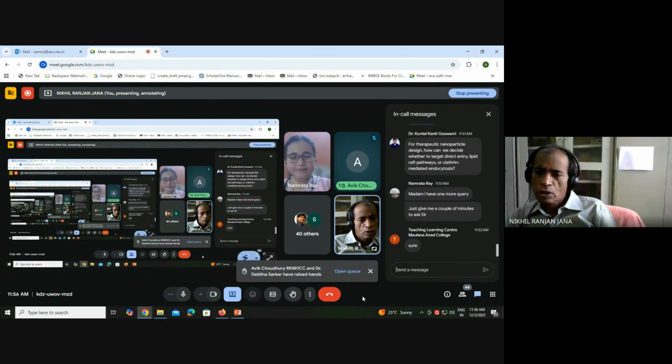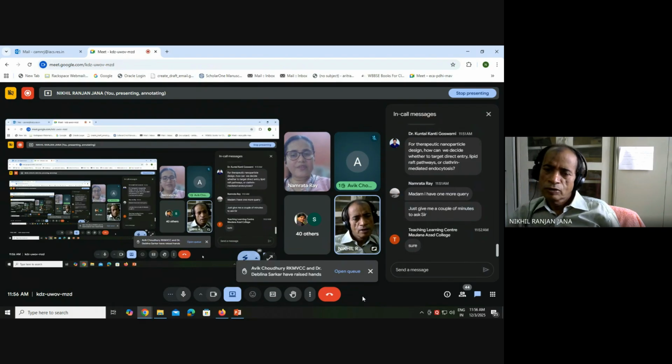Coating kind of thing. So those coatings are important. In addition to that, you have to have your folate or other molecules at the right surface. So ideally nanoparticles should be primarily covered with your PEG or dextran, and then a few folate, so that the only interaction is because of your folate receptors, nothing else. So your design has to be like that.